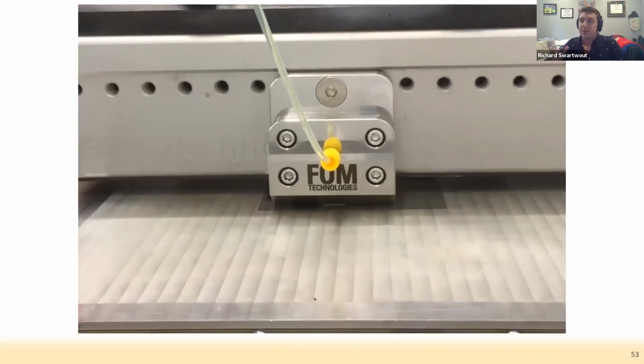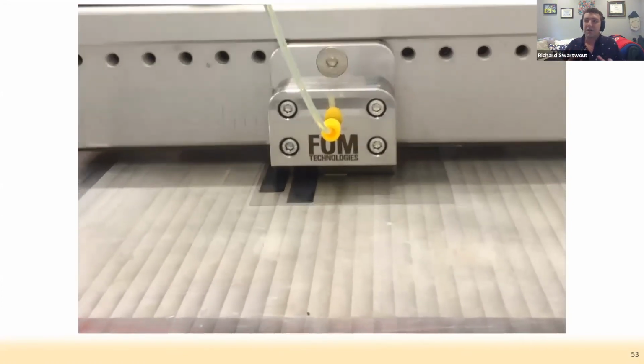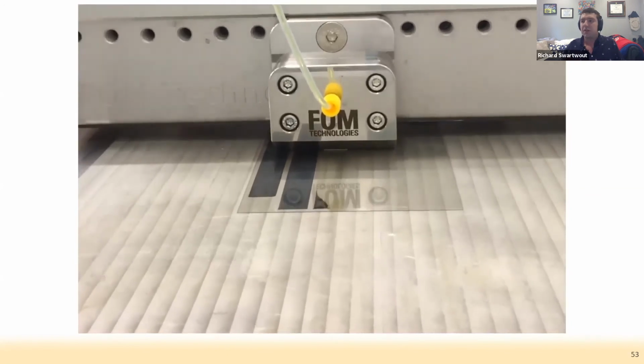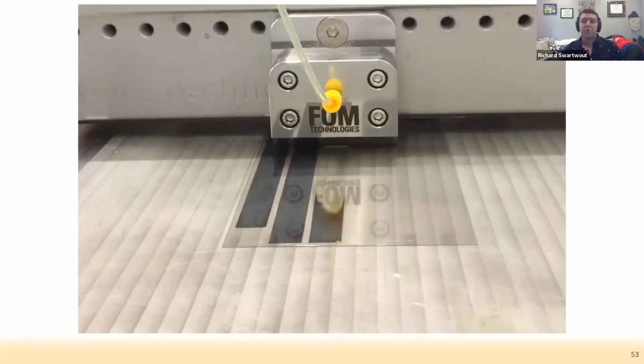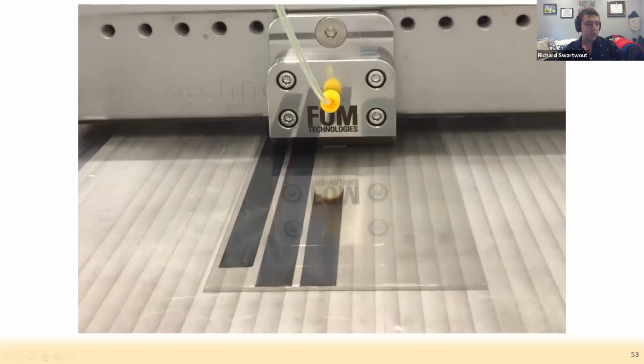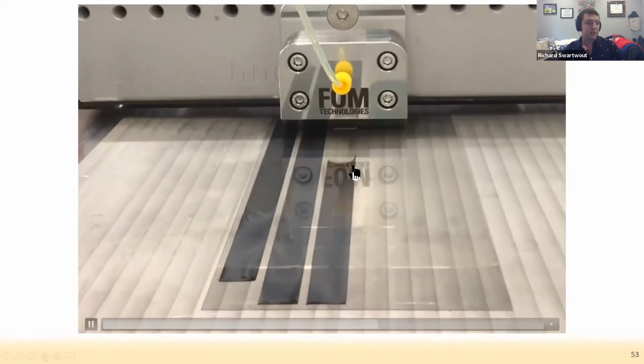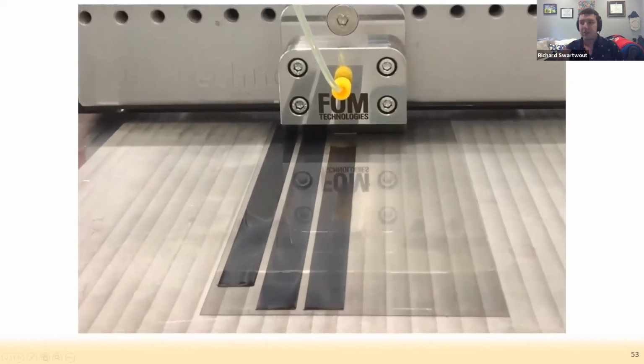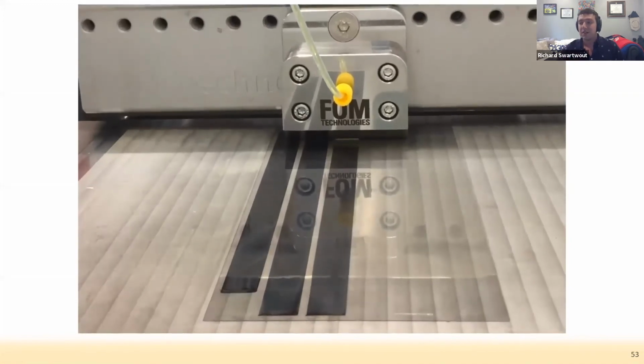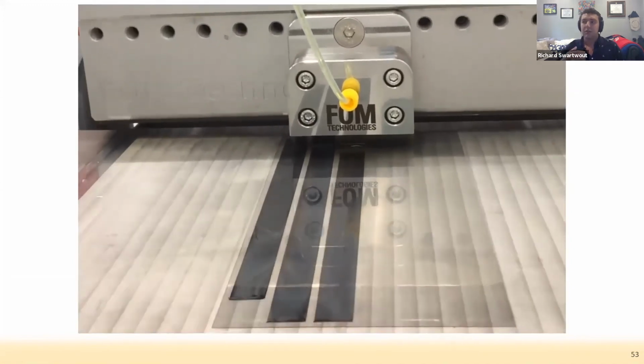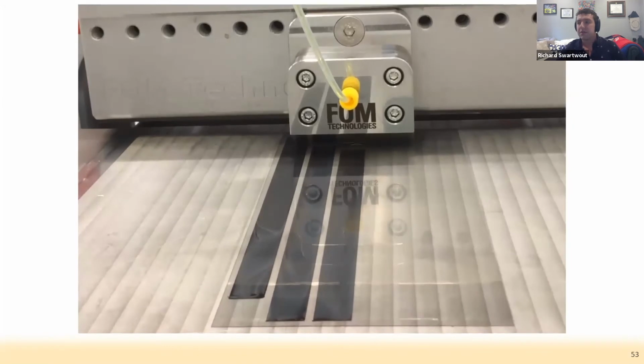So shown here is the THF methanol ink at about 0.9 meters a minute, for a frame of reference on speed. You can see that there's a very defined length, about a few centimeters, in which the THF and methanol dry and create that crystallization front as you see there.